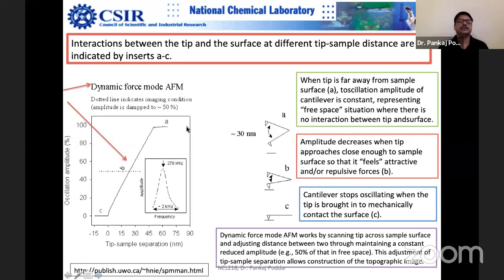And this is the oscillation amplitude, as I mentioned, against tip sample separation in nanometer. When the tip is far away and there is no van der Waals force, you can see that the tip amplitude has no change, it is constant. As soon as the tip sample distance starts going down, this amplitude starts going down, and when the tip is touching the surface, there is no oscillation because the tip is grabbed by the surface. So there is zero amplitude. You can see this flat line here because the tip is so far that there is no force. And here you have already reached the repulsive force and the tip is touching. So this is also shown with this amplitude change. So this is another way of showing.